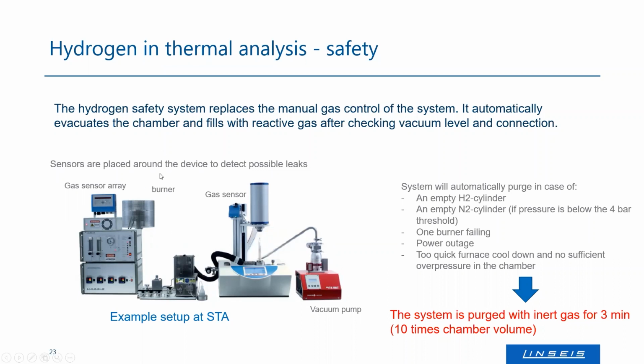what happens. In case a burner is failing, there is a power outage, or the furnace is cooled down too quickly and there is a risk of insufficient overpressure, this automated control system makes sure there is no risk when operating with this complete setup. If the system brings the system to a safe state, it purges with inert gas for 3 minutes, around 10 times the chamber volume, to get rid of the hydrogen in there. So you can open your system anytime it has cooled down in a safe state, and there's no risk of releasing hydrogen, causing explosions, burns, and whatever.